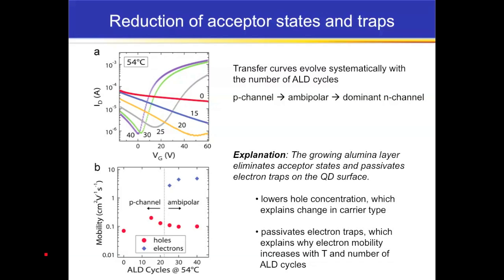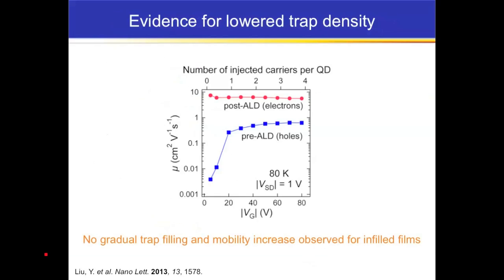And we think what's happening here is that essentially the carrier polarity change from P channel to N channel is because we're lowering the hole concentration by eating up acceptor states due to this ALD process. And we believe that the improved electron mobility is due to the fact that we're passivating some of the electron traps within the material. And we can pick this up by the dependence also of electron mobility on the temperature of the ALD process and the number of ALD cycles. So you can see that the electron mobility slightly increases here as we increase the number of ALD cycles. And so we really think that this is an effective, it's not totally effective, but it's a pretty effective way to modulate and manipulate the surface states.